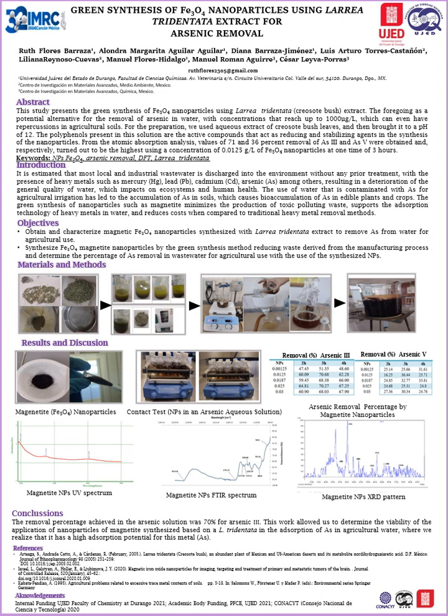VWR UV 6300 PC. The analysis was carried out in scanning mode in a wavelength range of 190 to 1100 nanometers, with a spectral resolution of 2.0 nanometers. The formation and stability of magnetite nanoparticles in aqueous colloidal solution was confirmed by the presence of absorption peaks at a wavelength of 270 nanometers, indicating the formation of iron oxide nanoparticles.